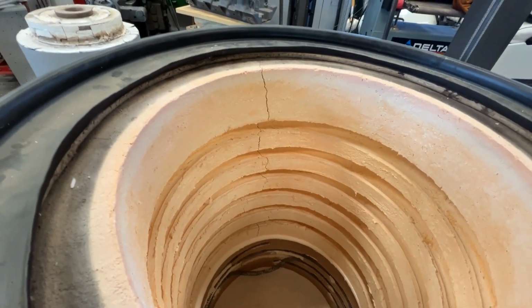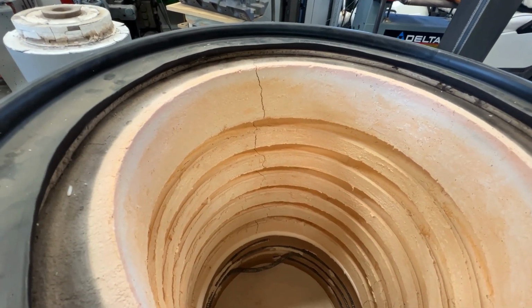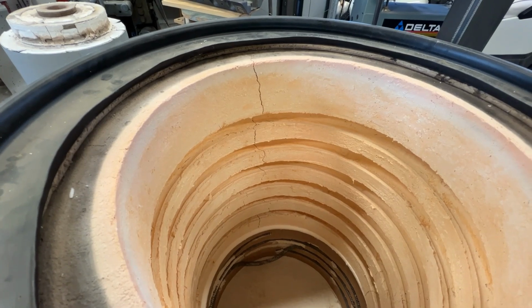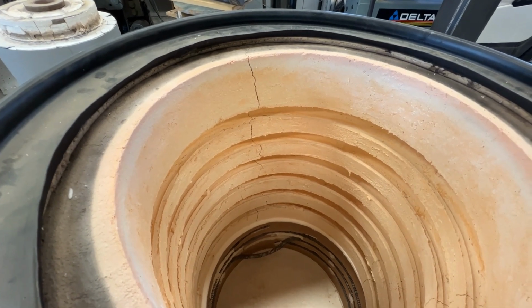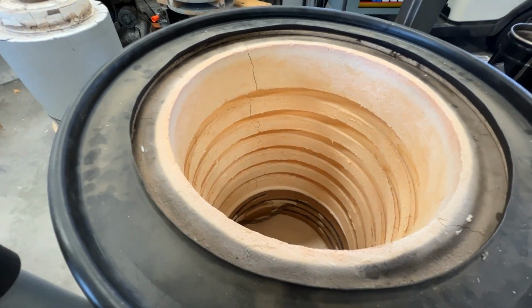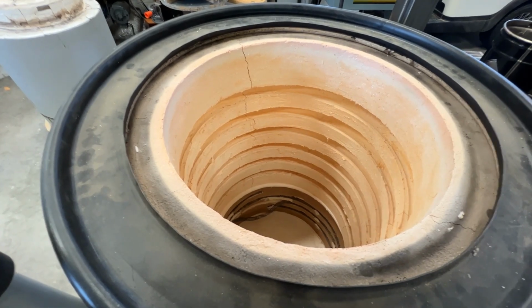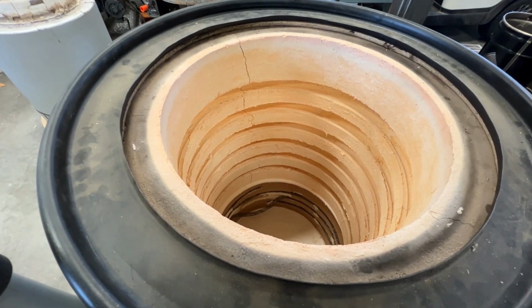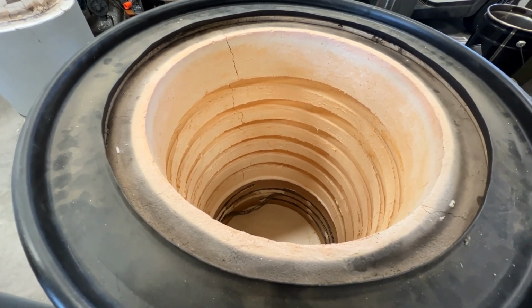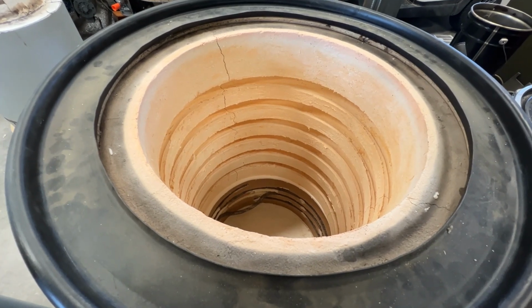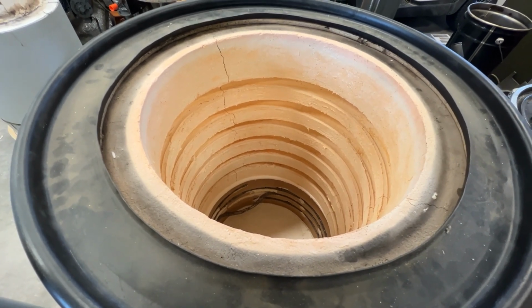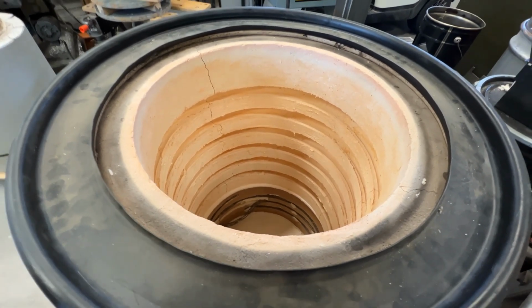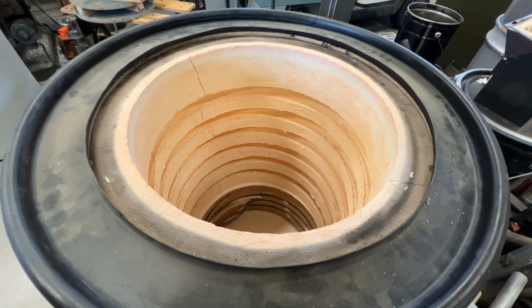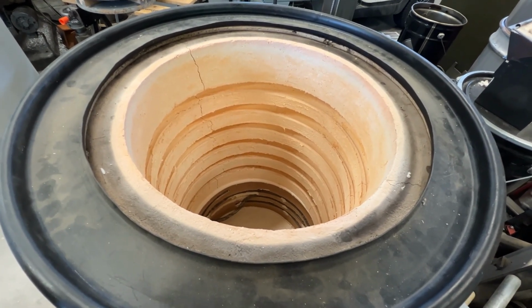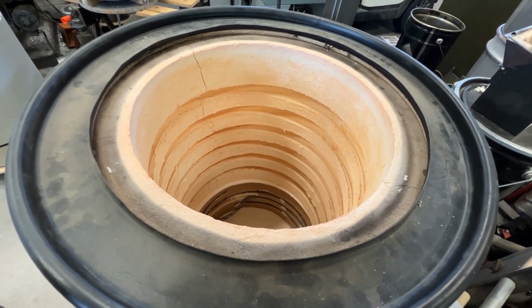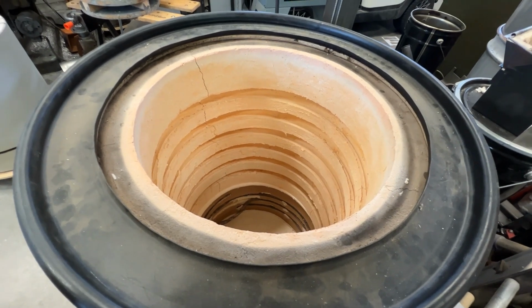So I'm not really sure what I'm going to do about that. I mean, some cracking is to be expected. It's because the inside expands so much more than the outside, because the inside's at 2000 F and the outside's basically at a couple hundred F. And that makes for quite a bit of stress build up in that monolithic block that I molded there. But I don't know, I might dig out the crack and patch it, but I've got a sneaky feeling that even if I do, all it will do is reappear.